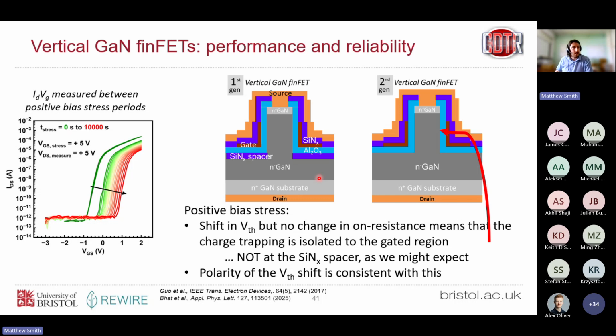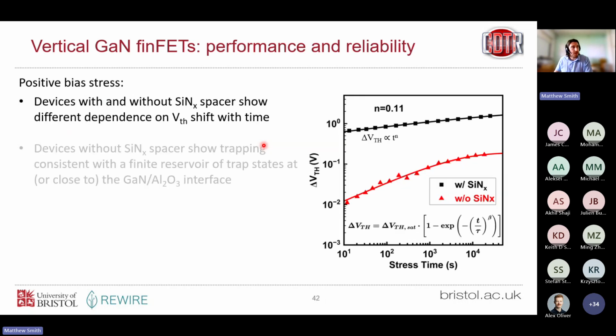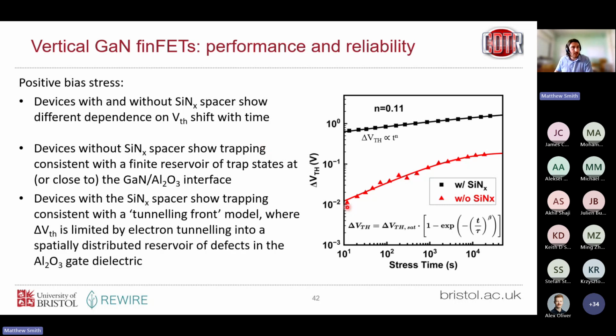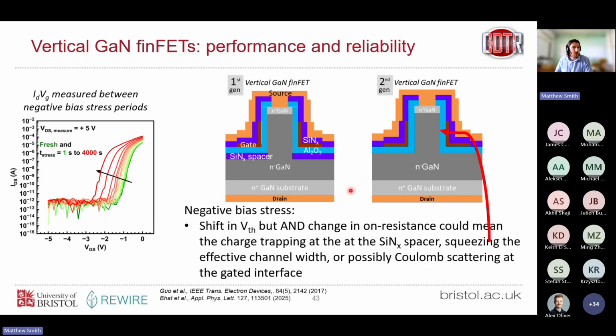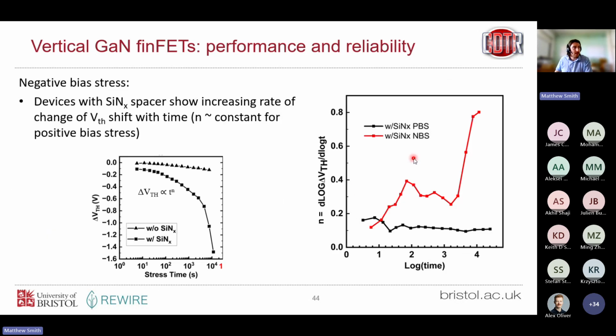So what we conclude then is that it's not actually the silicon nitride spacer itself which is causing this degradation. It's the process of depositing it and then removing it, which is introducing some defects on this sidewall here. So I won't dwell on this, but Chengji did some great work where he looked at the time constants and the relationship between stress time and threshold voltage, and found we have some tunneling front model where charge tunnels into the aluminium oxide dielectric. But essentially, same thing for the negative bias.